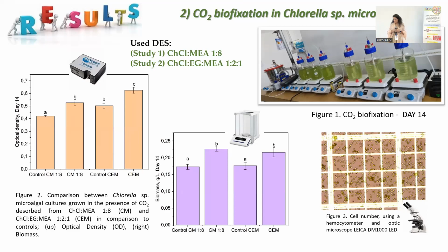For the biofixation part, we used the two solvents with monoethanolamine. Compared to the control group, we had supplementary development of the microalgae. We studied two main parameters: optical density using a UV-Vis spectrometer and gravimetry for the biomass determination. As we can see, for the optical density the ternary solvent had better results, and for the biomass, quite the same.